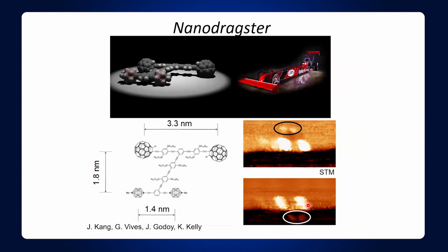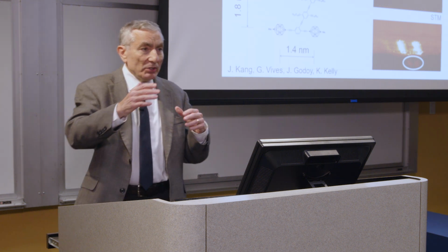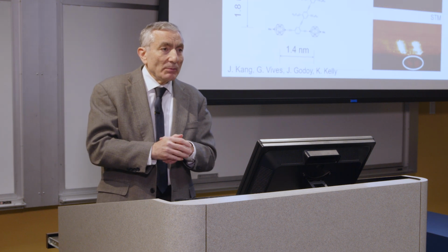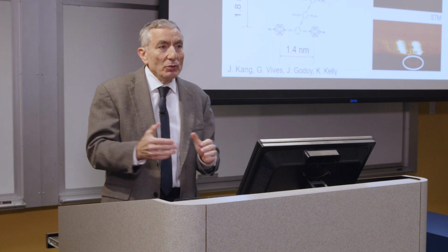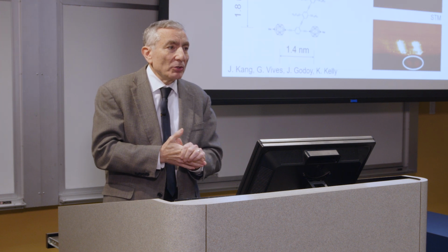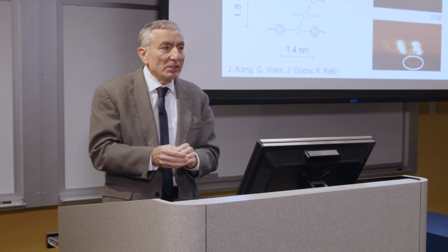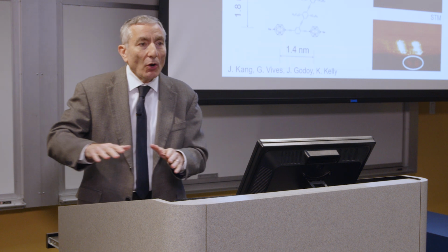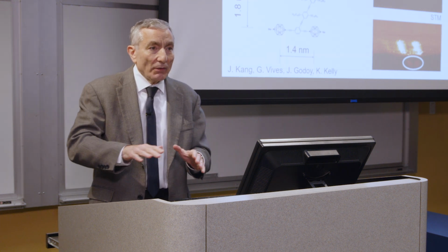And now what happens is when this starts to move, these little wheels don't stick nearly as much to this surface as the big wheels stick. And there's a reason for that. These are all pi electron systems, and they stick with about 2 eV bond strength to the gold surface. So much so that the way we got these to move across the surface, you can use the STM tip, or you can just heat the surface to 440 Kelvin. So you can heat it to a couple hundred degrees, 150, 180 degrees centigrade. And that's enough to get the cars moving, 200 degrees centigrade, to give it enough thermal energy.